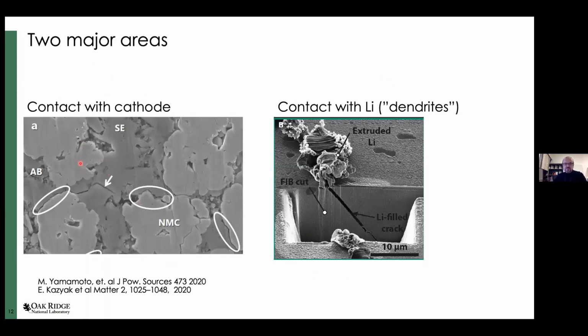They fail in contact with the cathode because of the repeated cycling. You have kind of a fatigue. Some of those cracks appear immediately. Some of them propagate with time. You have cracks at the interface between the active material particles and the electrolyte, and you have cracks in the electrolyte itself. So this example of the LPS with NMC, I believe this was from the Yamamoto group